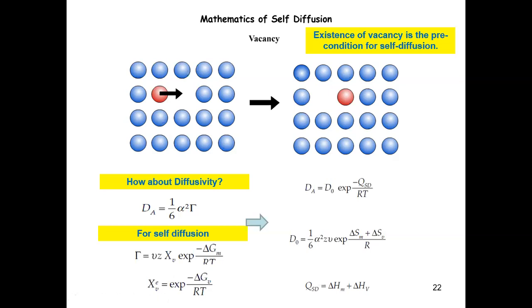Okay, so again, the take-home message is that you can actually use the same trick to measure the self diffusion as we did before, right? If you do the diffusivity measurement at different temperatures, you can do an interpolation as a straight line if you take the logarithm of these two, and you can estimate these different parameters, D naught and QSD.